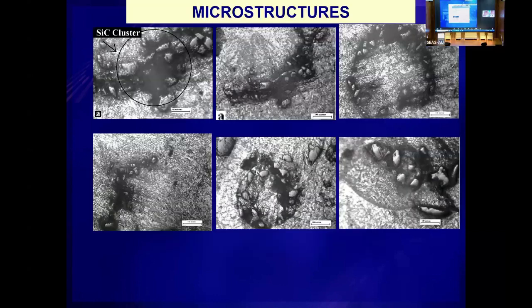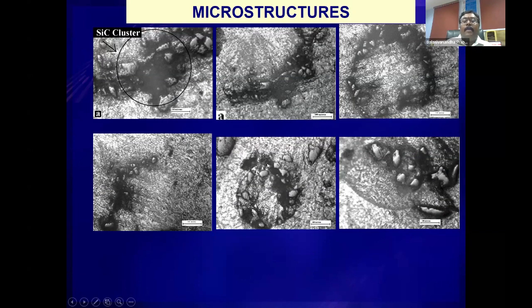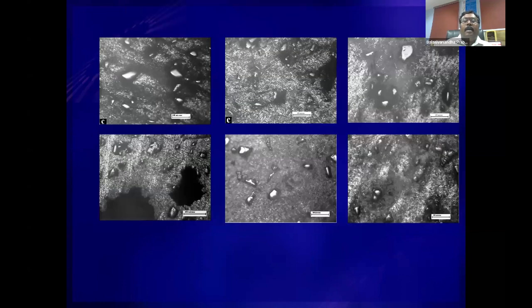So these are some of the microstructures in our laboratory that we have cast. You can see the particle distribution, which in some cases is agglomerated. The particles are agglomerated. In some places the aluminum is left without any particle presence. That means the microstructure is highly inhomogeneous. It is not a homogeneous microstructure in some of the cases. In some of the cases, we were able to achieve microstructure uniformity. That means the particles are well dispersed and there are no agglomerations here.